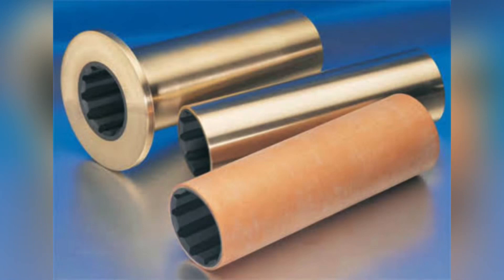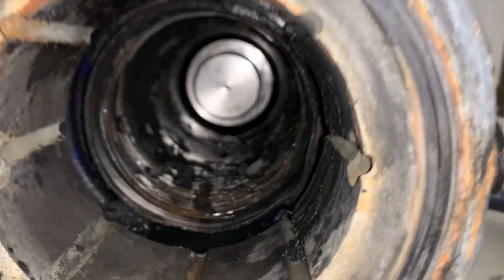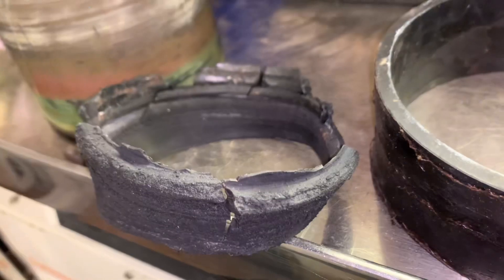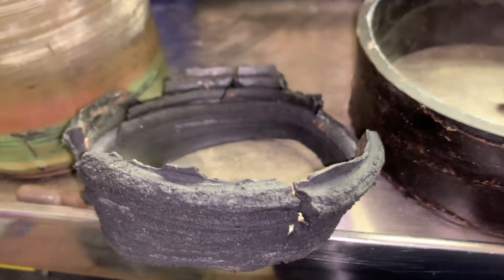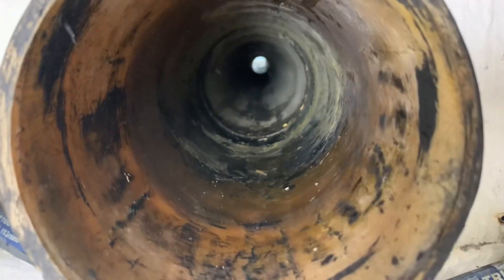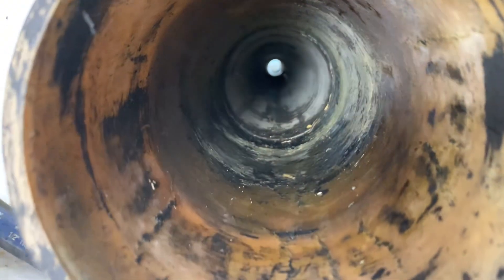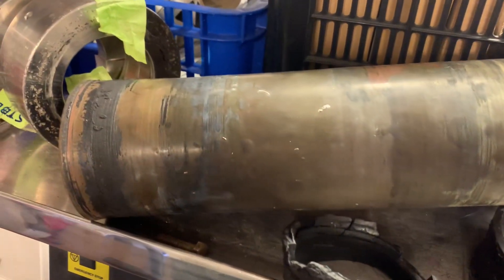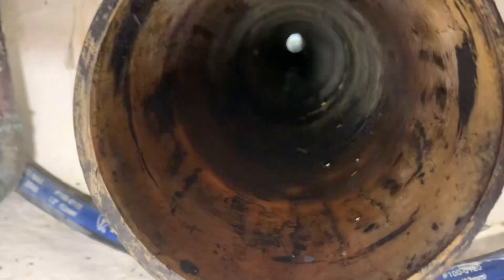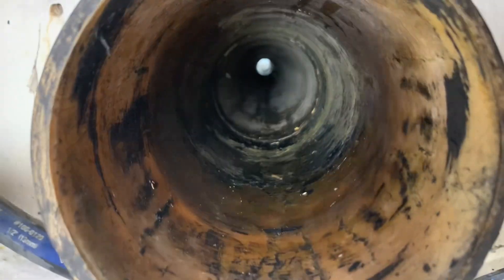Either type is recommended for use on a fiberglass boat. The rubberized surface of the interior starboard side bearing, as suspected, was severely damaged. The rubber material appeared to have become granulated and had melted into a collar around the shaft. The housing was observed to have some cracks in the fiberglass, mostly in the forward three inches. The bearing outside diameter was significantly undersized, measuring almost two millimeters smaller than specifications in some areas. The cracks in the forward part of the starboard bearing housing did not appear to be deep, and no cracking or leaking was observed on the exterior paint or gel coat of the housing.